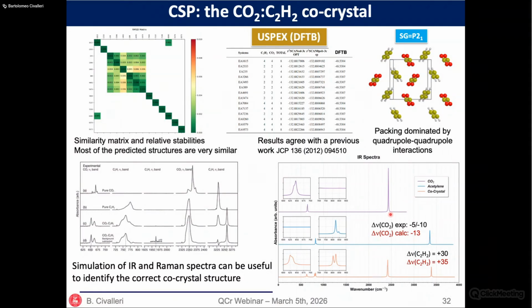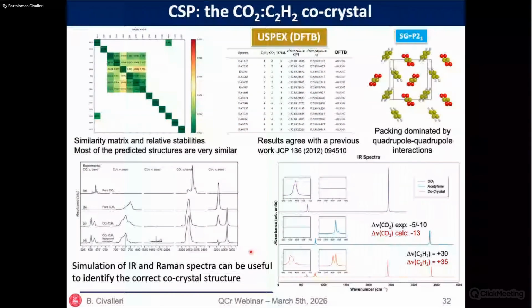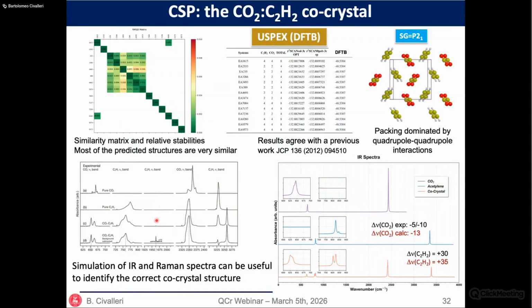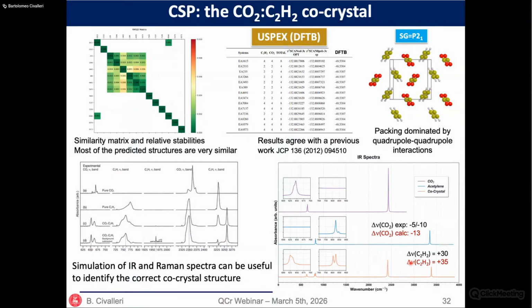And even if of course the peaks do not coincide with the ones in the experimental spectrum, because we are running calculations at the harmonic level, if we look at the shift of the peaks that can be observed when passing from the pure crystal to the co-crystal, we computed and predicted more or less the same blue shift for carbon dioxide and the red shift for acetylene. So this means that the structure is well reproduced.